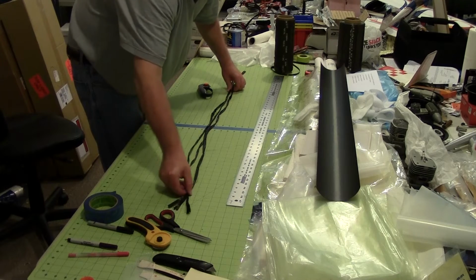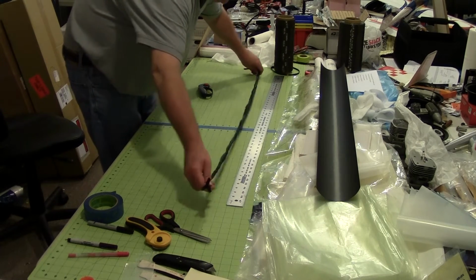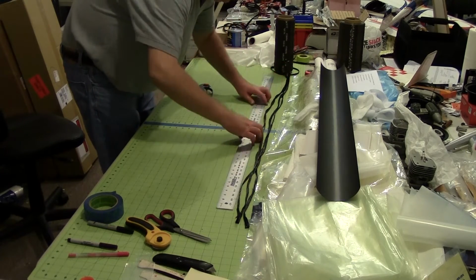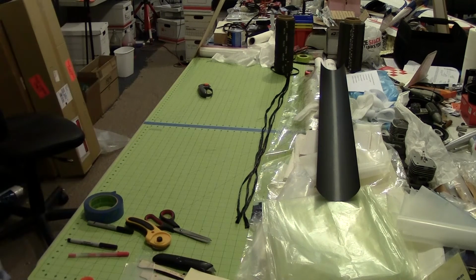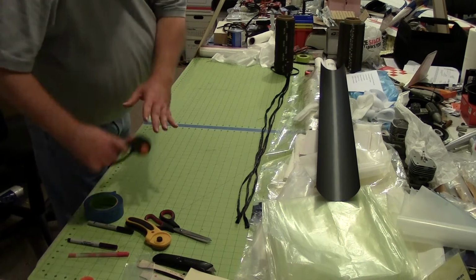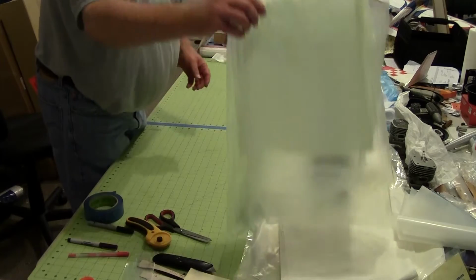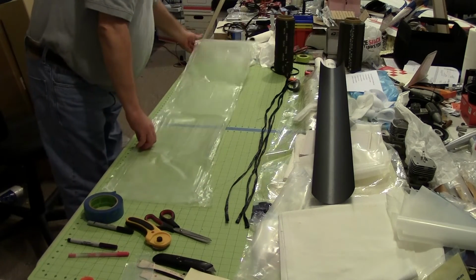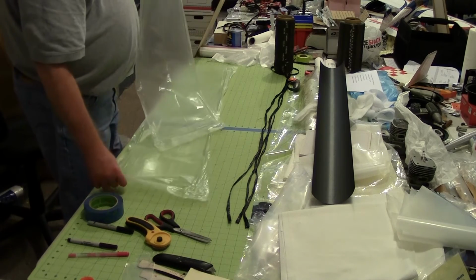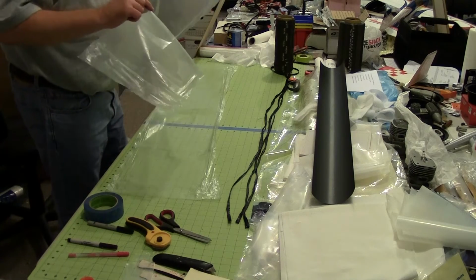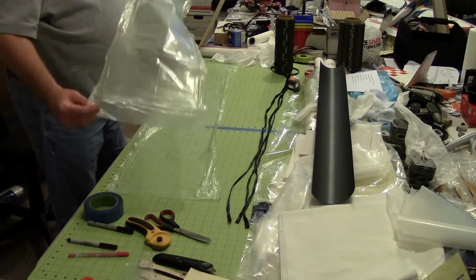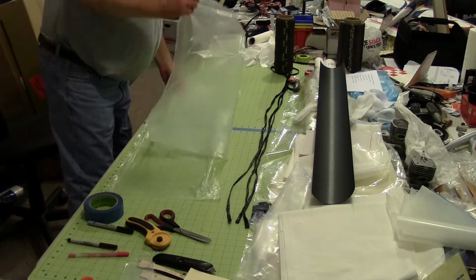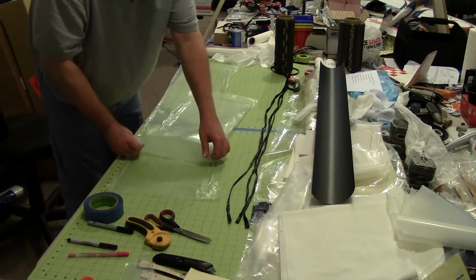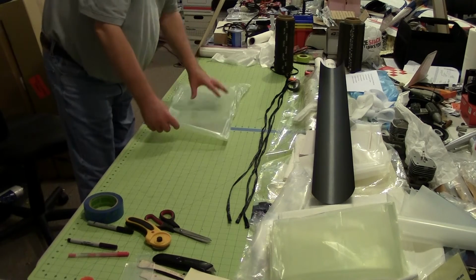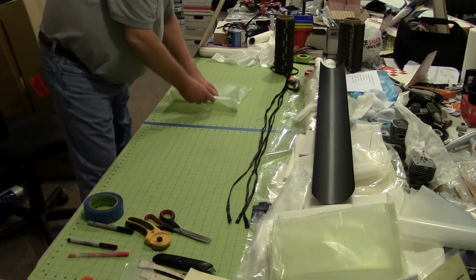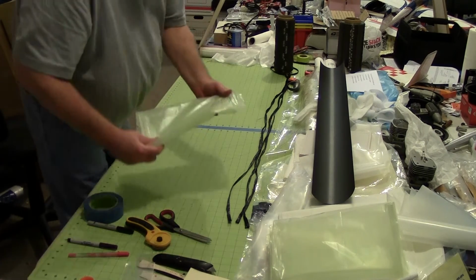So I use 3 pieces of 50K tow for the leading edge, and I'll just leave it sitting right here. The other thing is that I use porous release film between the balsa and the foam. I get this particular film from ACP Composites. I'm generally able to reuse it, so that's kind of nice. Saves a few bucks per wing. But the nice thing about it is it lets the airflow and the vacuum work really well, and you don't have any spots where you don't get adhesion.